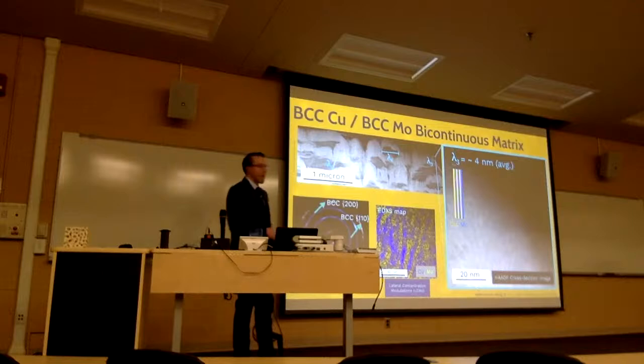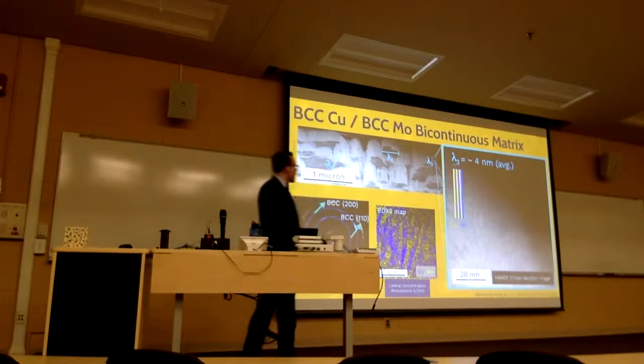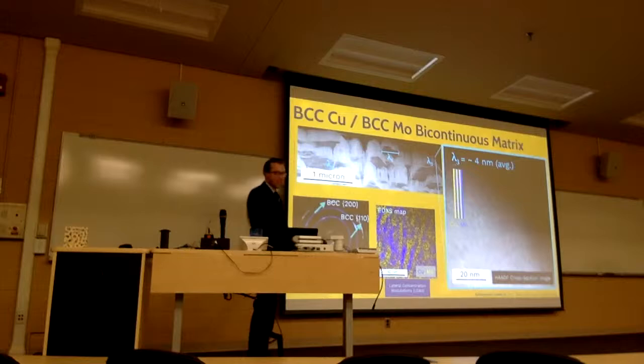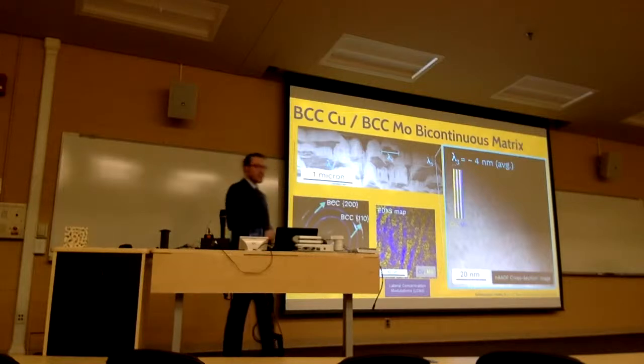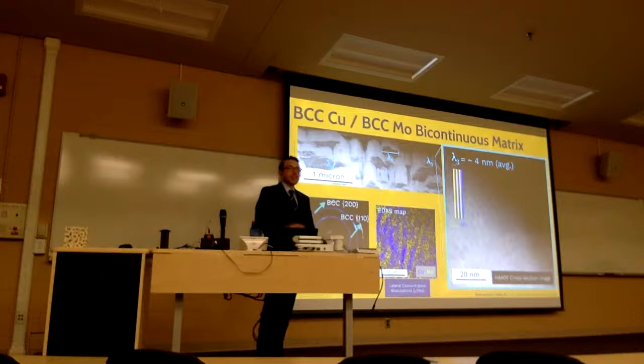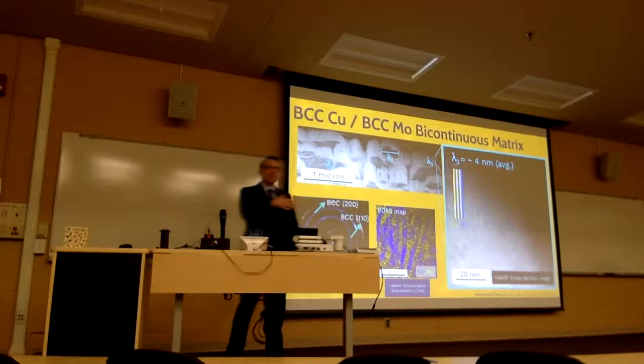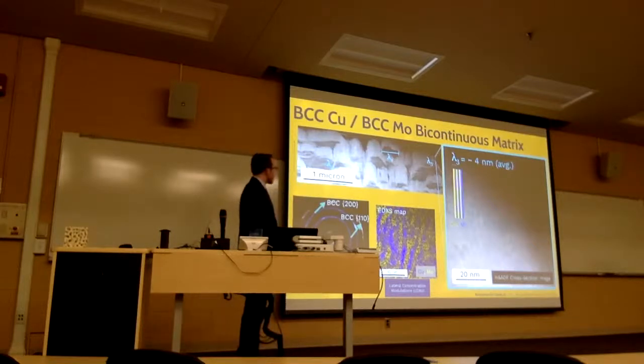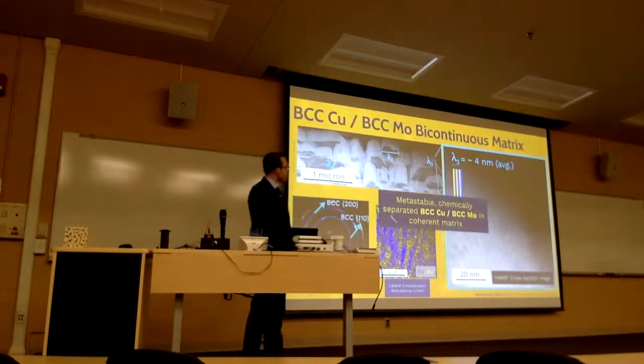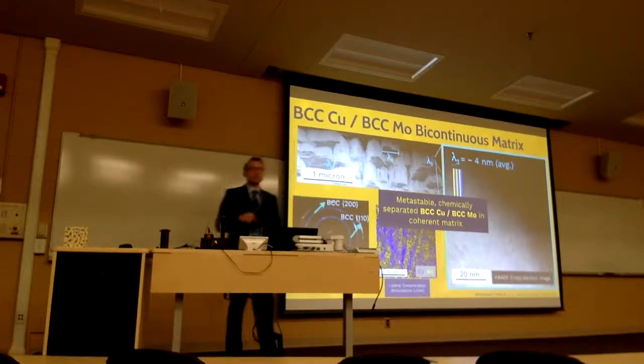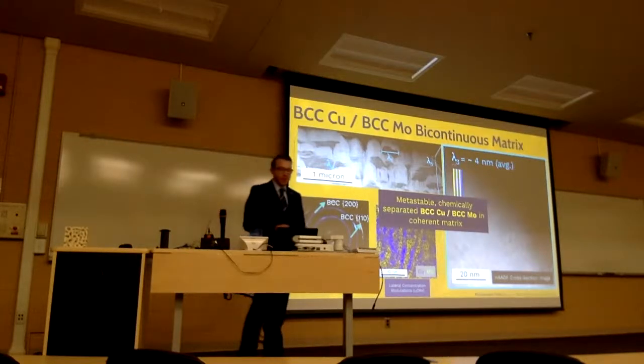At lambda 3, what we have is something that we're all familiar with now, this LCM or lateral concentration modulations of copper and molybdenum at a small length scale. You can see that in the chemical imaging here. And the crystallography of this region of the sample is very interesting in that in this case, we have pseudomorphic copper. So whereas before in the islands we had pseudomorphic or metastable moly, here we have metastable copper in the BCC crystal structure in this matrix of copper and molybdenum. So in summary, we have a metastable chemically separated BCC copper, BCC moly in a coherent matrix.